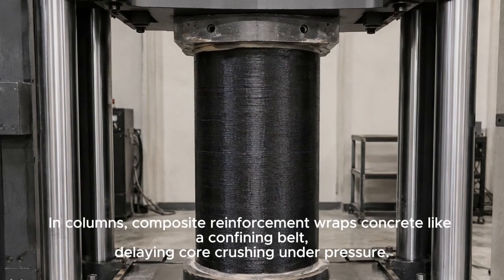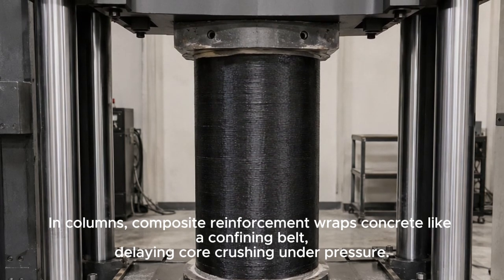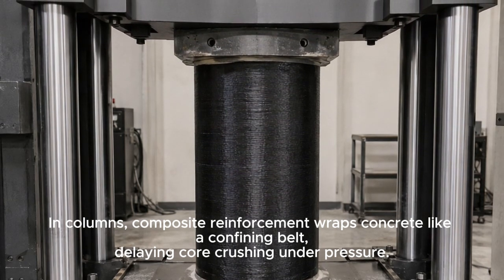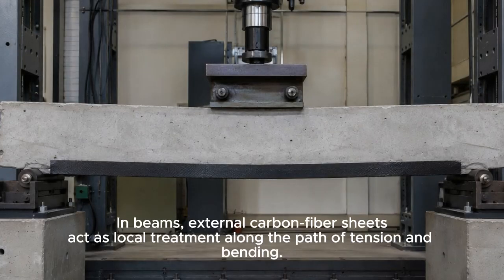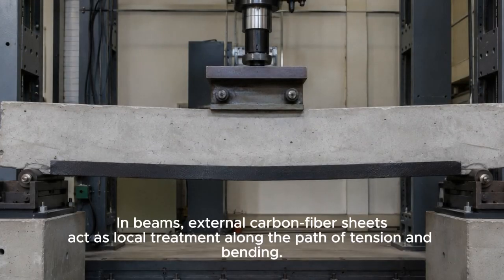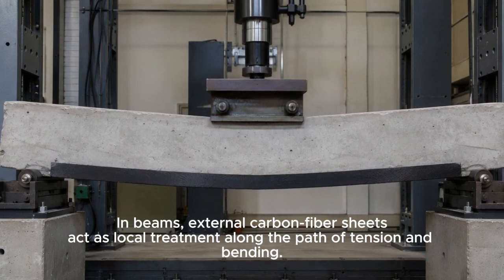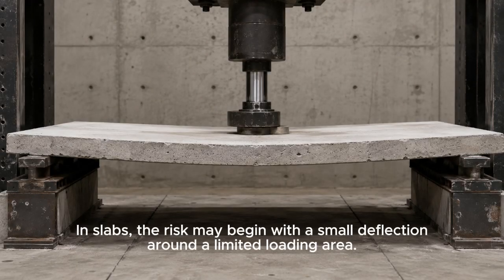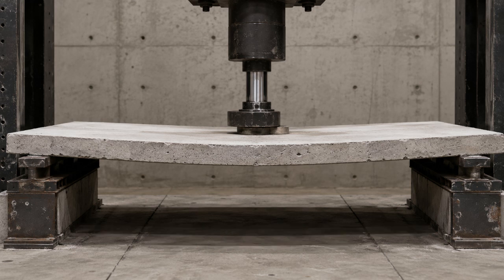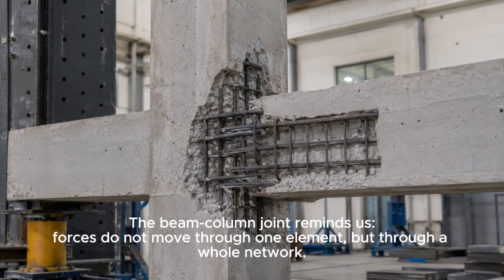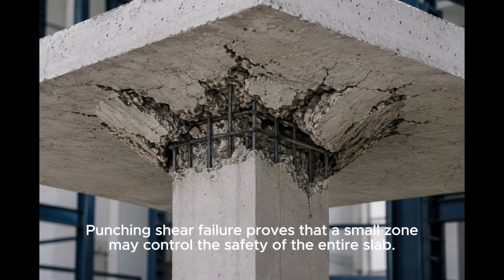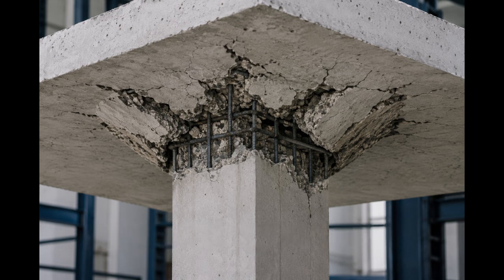In columns, composite reinforcement wraps concrete like a confining belt, delaying core crushing under pressure. In beams, external carbon fiber sheets act as local treatment along the path of tension and bending. In slabs, the risk may begin with a small deflection around a limited loading area. The beam column joint reminds us, forces do not move through one element, but through a whole network. Punching shear failure proves that a small zone may control the safety of the entire slab.